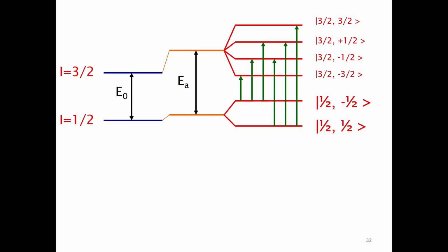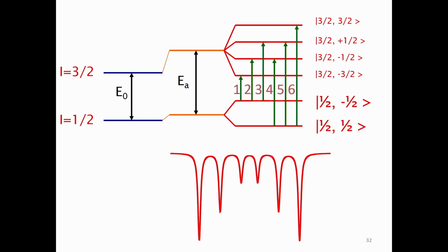Sometimes it's possible on some spectra to observe some forbidden transitions. So, 6 lines. I will discuss the intensity a bit just after. You can correlate the intensity, and the distance in terms of energy, with the position of lines. The distance between, a priori, the external peaks corresponds to the hyperfine field. I mention a priori because sometimes we will see that they do not correspond to the external peaks, the more intense peaks.